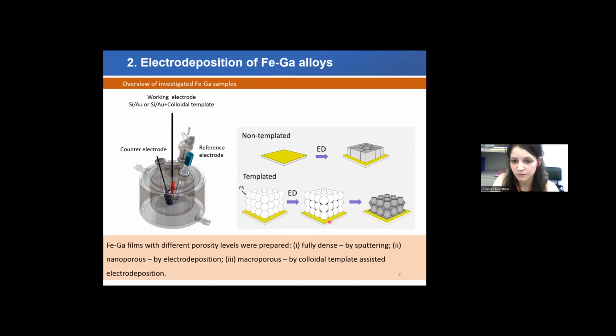So during electrodeposition, the film was growing everywhere between the spheres. And after electrodeposition, we could remove the spheres in an organic solvent, in tetrahydrofuran. After the spheres are removed, we are left with this kind of porous structure in iron gallium films. We also prepared an iron gallium reference sample by sputtering. This is a physical deposition method. So we will consider this reference sample to be fully dense and we used it for mechanical and for magnetic measurements as a reference sample.